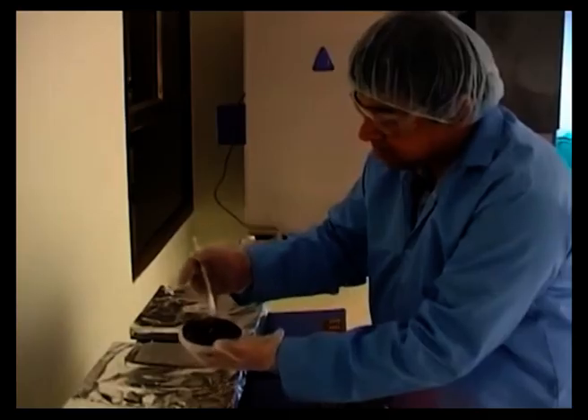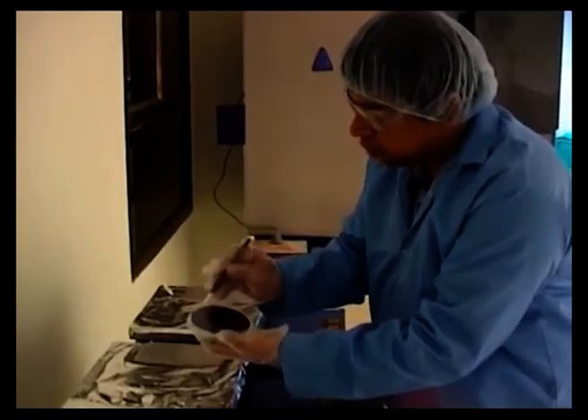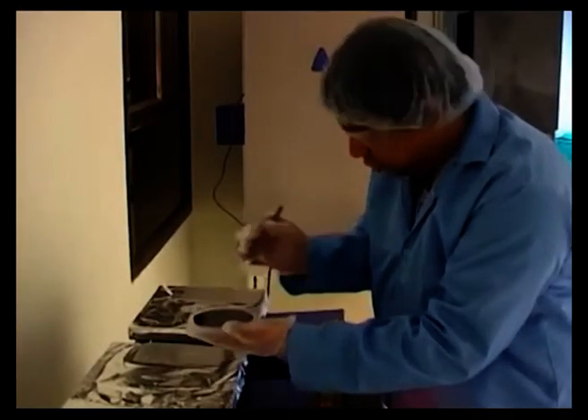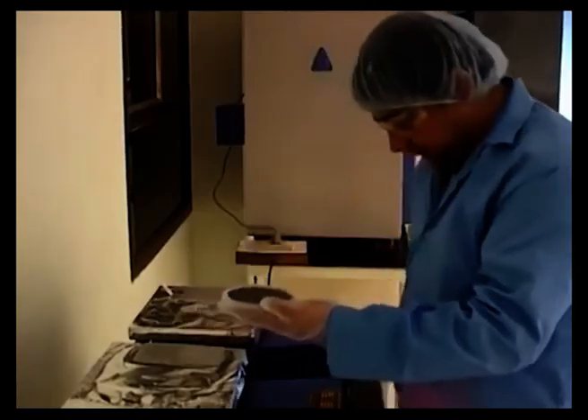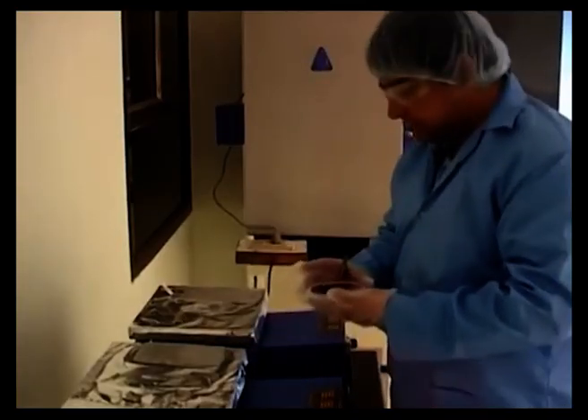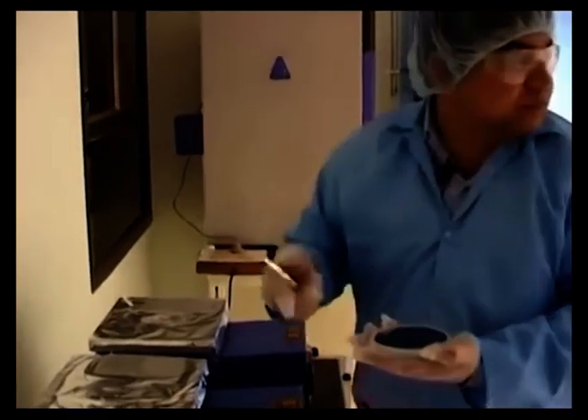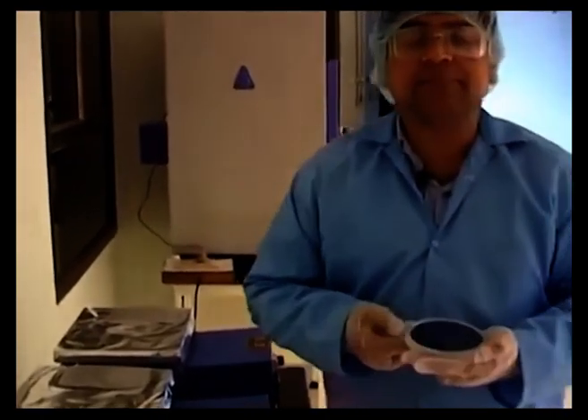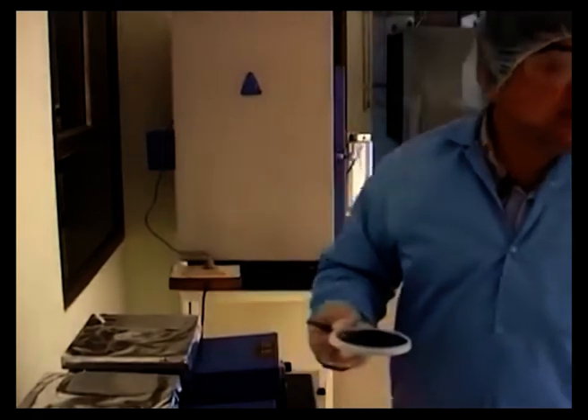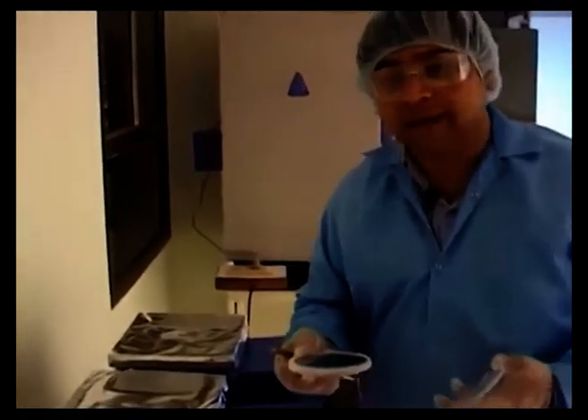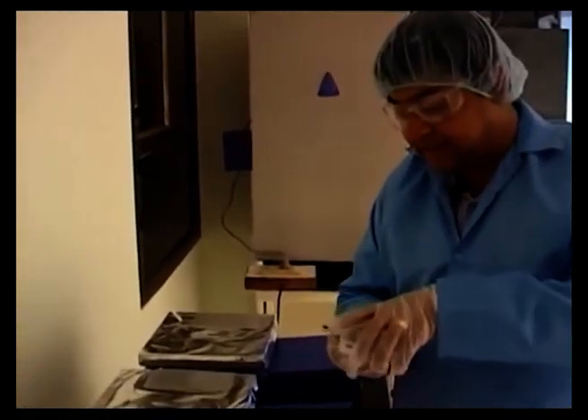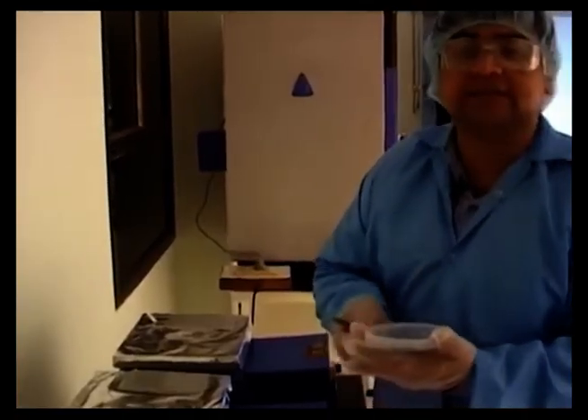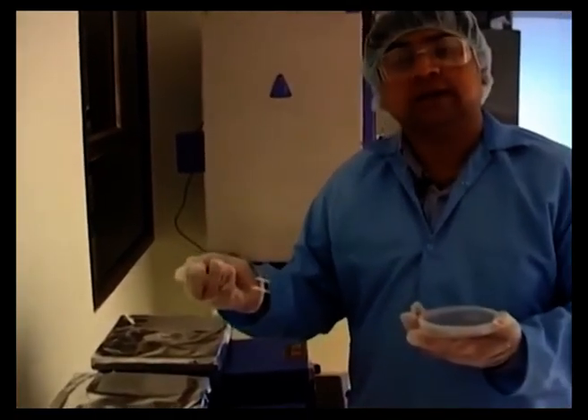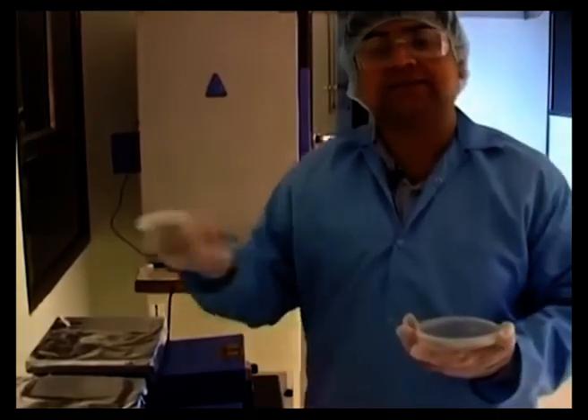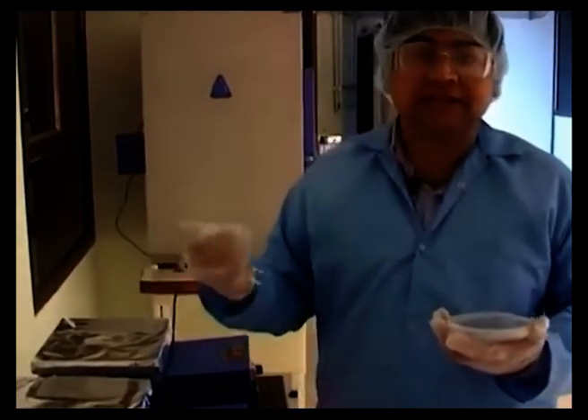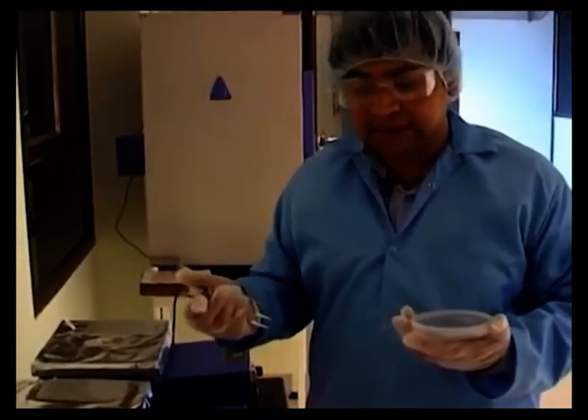It is always a good idea to hold the heated surface at room temperature and let it come back to the ambient room temperature for the film to have the least possible undulations and warping. We'll just cover it in case there is any dust accumulation on the surface. Another thing I want to point out is that the environment in which this coating process is carried out is a very clean environment.